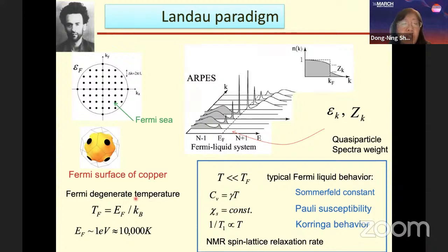...a characteristic Fermi-degenerate temperature. That temperature is determined by the Fermi energy, and for copper it is around 10,000 K. Then we can examine if copper has typical Fermi-liquid behavior by measuring the specific heat, spin susceptibility, and the 1/T1 NMR spin-lattice relaxation rate.